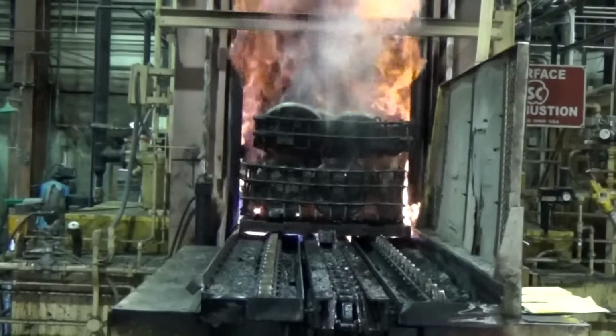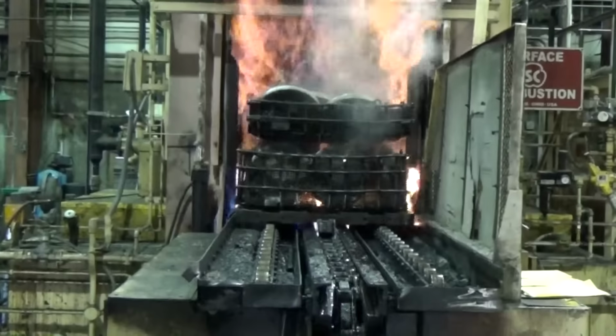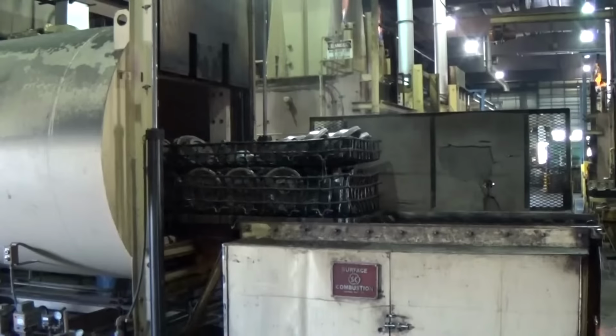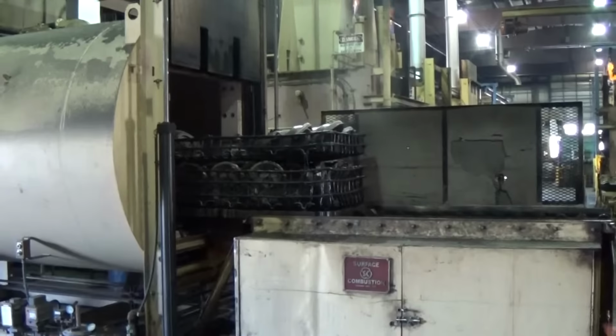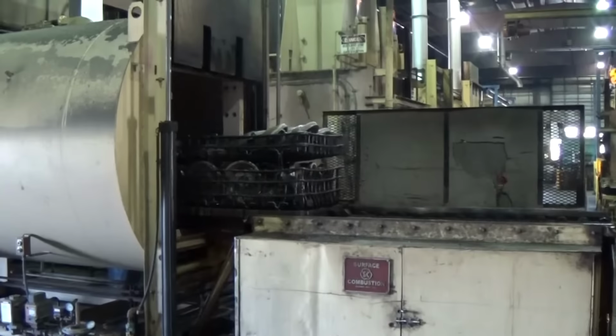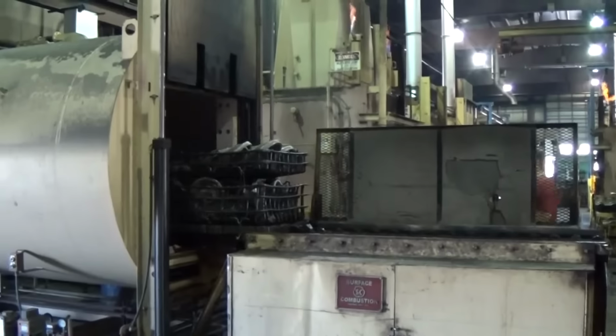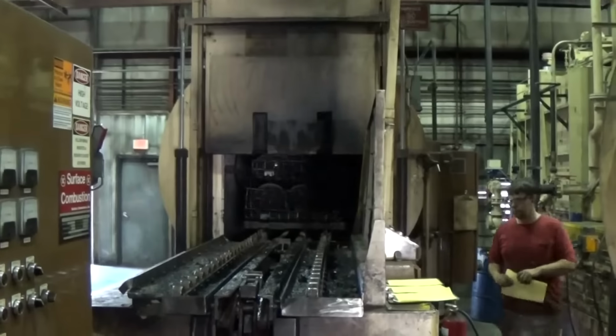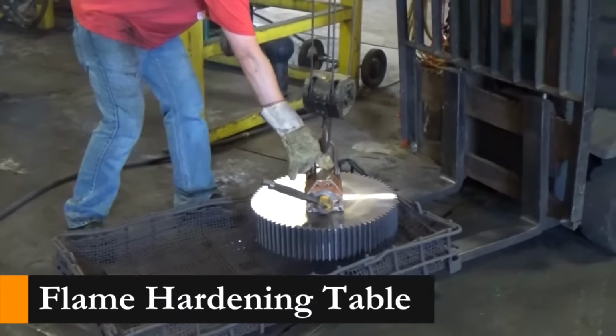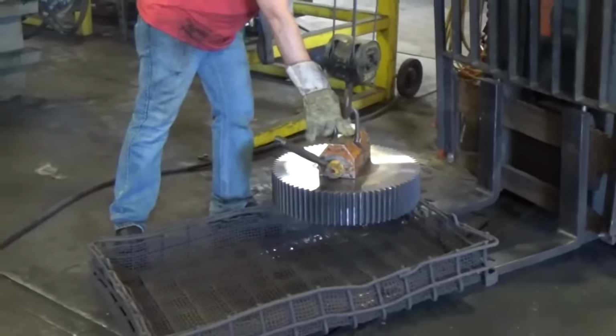Following the completion of a quench cycle, the load is removed out of the front chamber with a charge cart. The smoke and sheen seen on the parts is from excess quench oil. Immediately after quenching, these parts are transferred into a tempering oven, which reheats the load to about 1000 degrees Fahrenheit. This greatly improves the toughness properties of the parts.